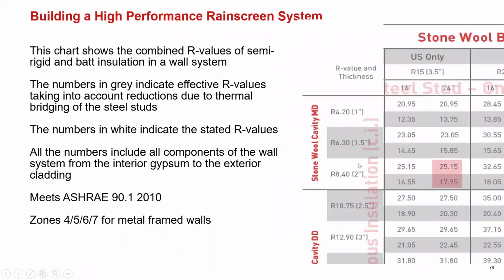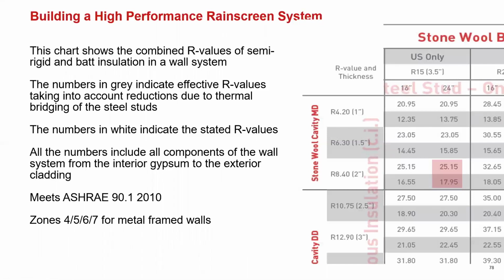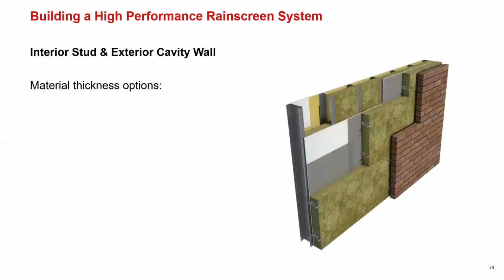You would typically need to see on the bat insulation 3.5 inches of stone wool to get to an R15, and then 2 inches of stone wool to get to an R8.4, which would exceed that 7.5 requirement. It's important to note that that'll get you a nominal R23.4, but the effective R value is going to be about an R18. Right, so we can't forget that when you're stuffing bat insulation between metal studs, that's going to derate your overall assembly, right? You've got some thermal bridges there that need to be accounted for.